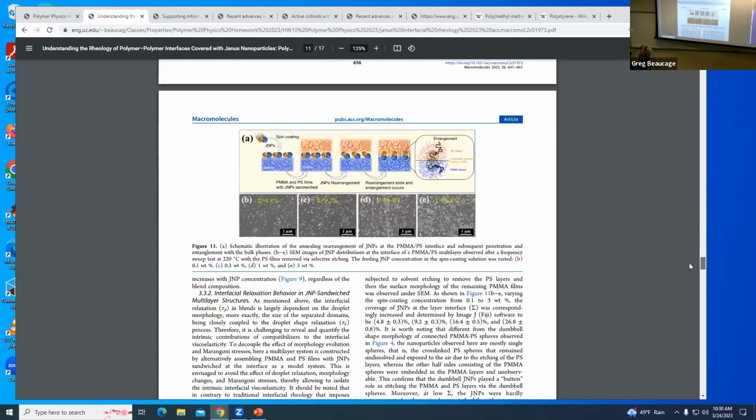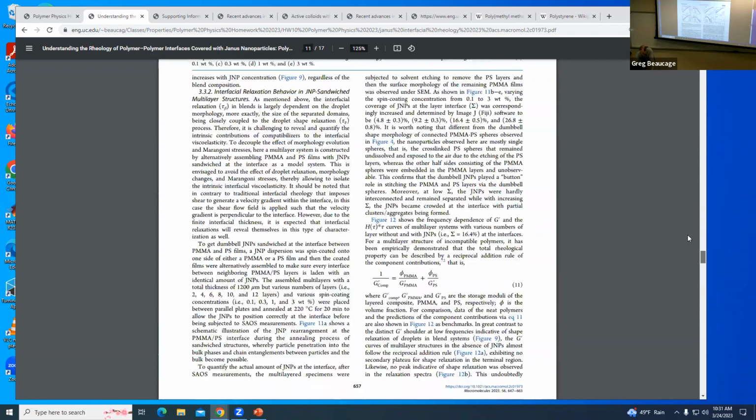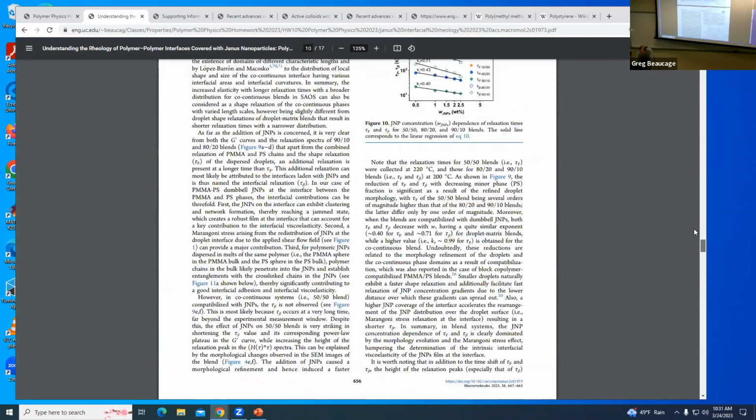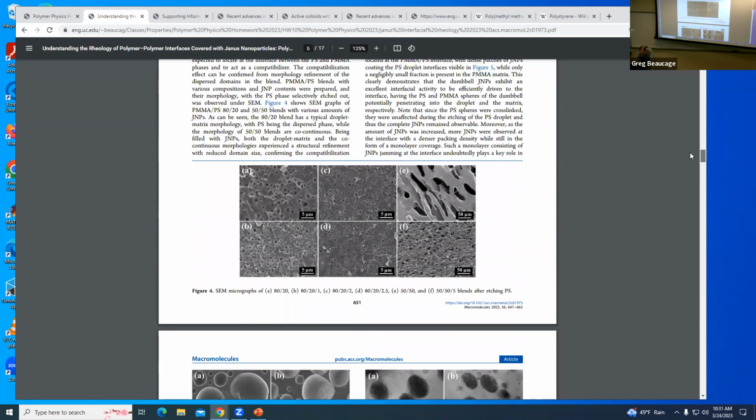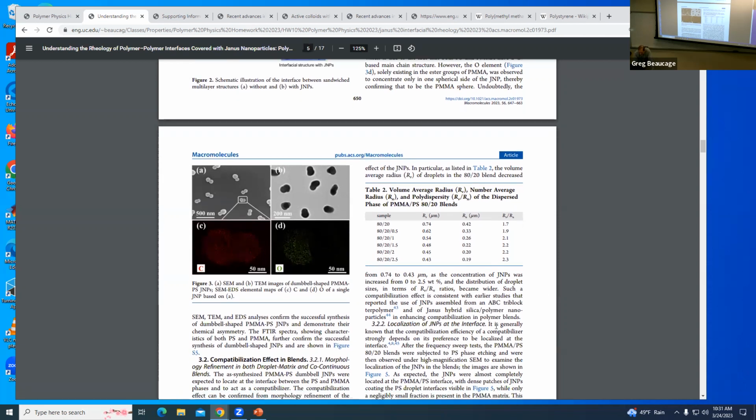There's the one color graphic in here somewhere. Here. So see, he's got the two Janus particles. One's styrene, one's PMMA, the one on the left, and the other one's styrene. Then he does oxygen mapping. He gets just the PMMA part, the oxygen shows up. He zooms in on that, does the EDX on it, and gets that. So that kind of works out. This is carbon, this is oxygen. All right, so he's demonstrated it pretty convincingly.